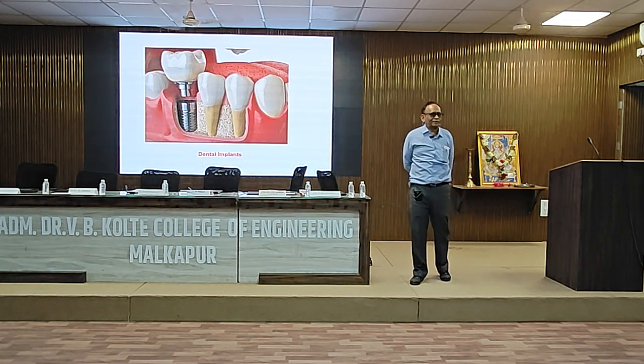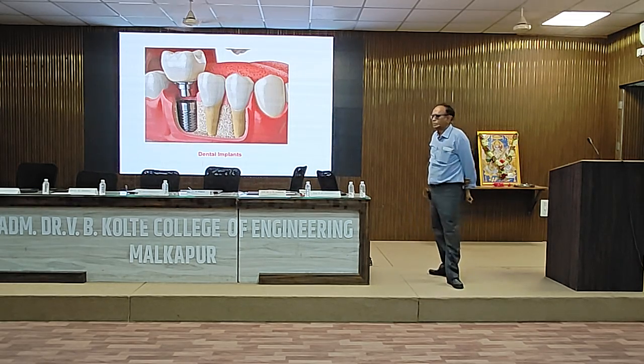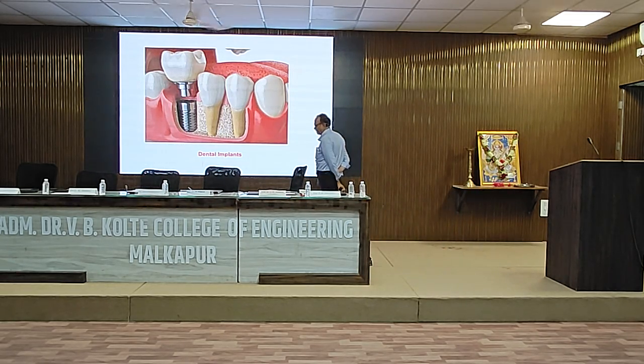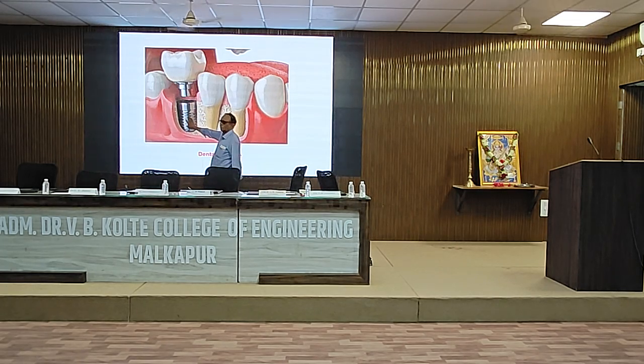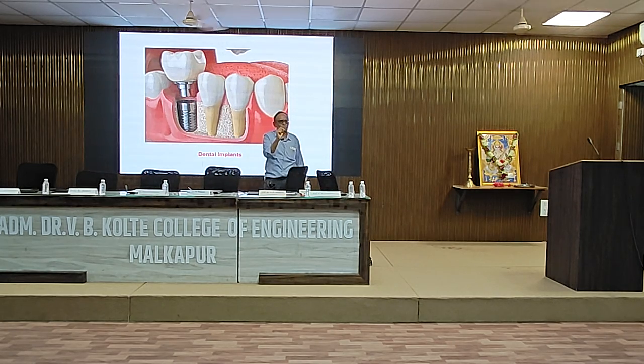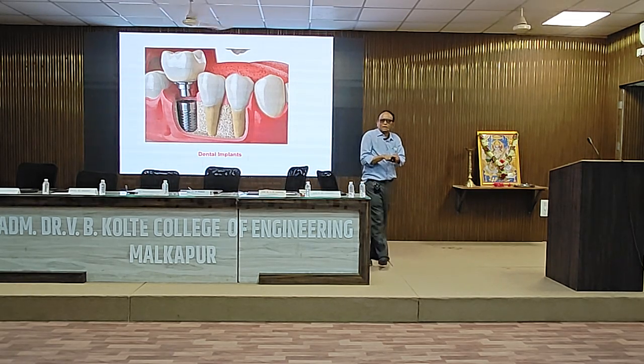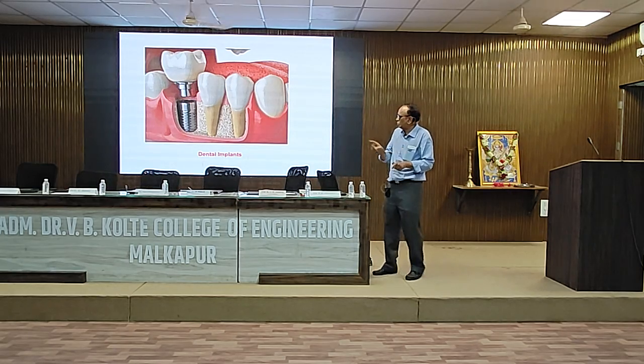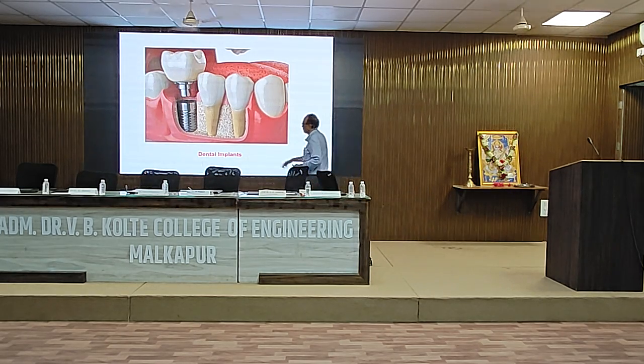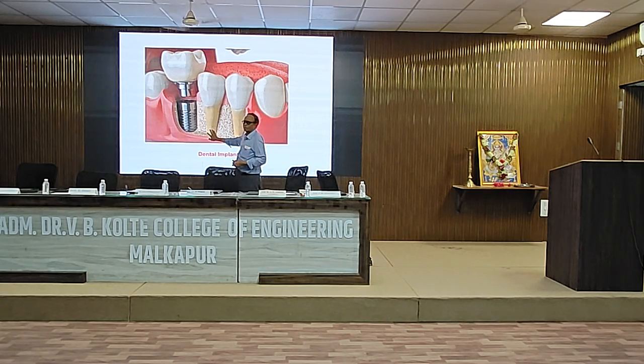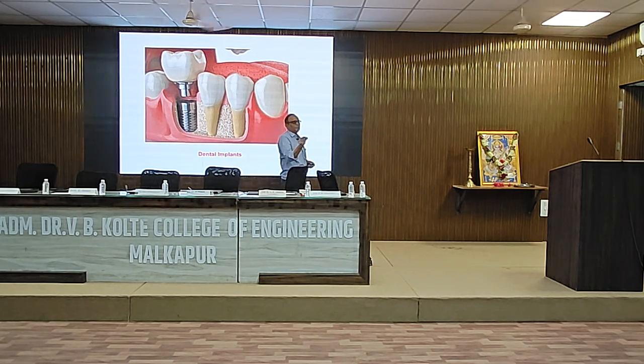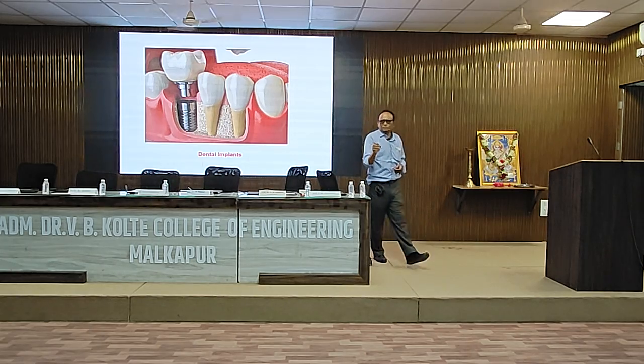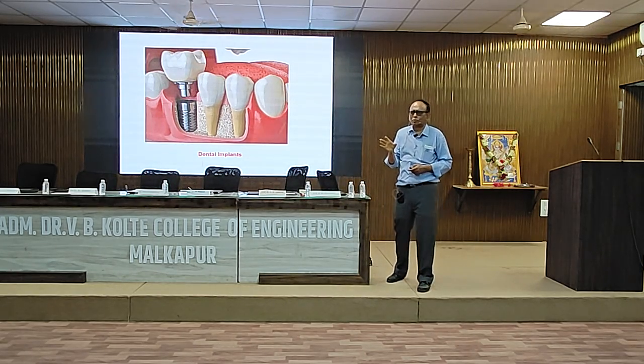See, the dental implant that is implanted into the patient. Basically, there is a titanium 6 aluminum 4 vanadium root. The surgeon drills the hole, puts that titanium 6 aluminum 4 vanadium assembly into the jaw, and it is sealed. After 3 months, now if there is a coating of hydroxyapatite on this, hydroxyapatite is Ca10(PO4)6(OH)2. Now this is the mineral that resembles the mineral phase of the bone.